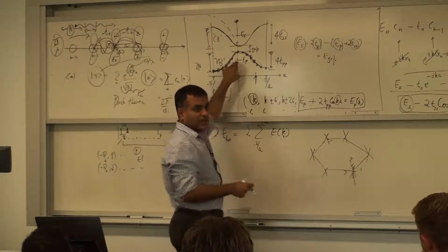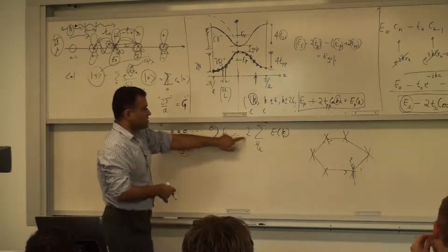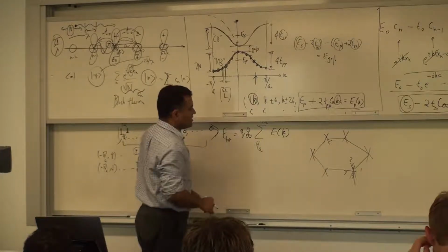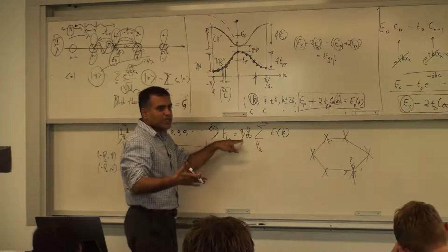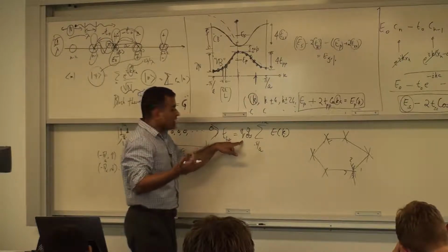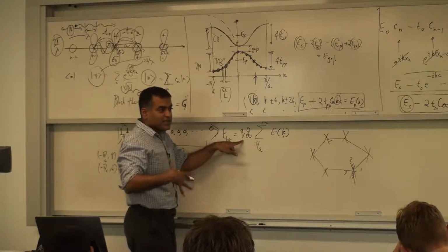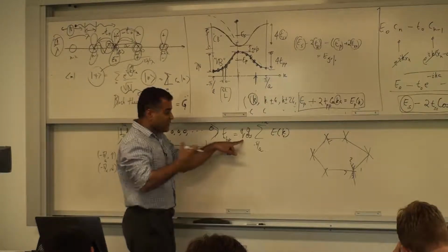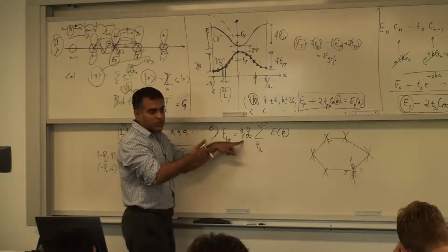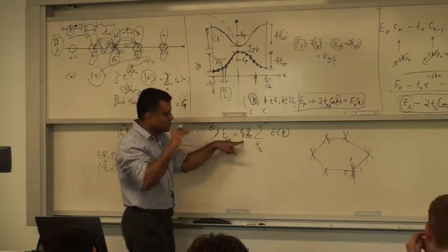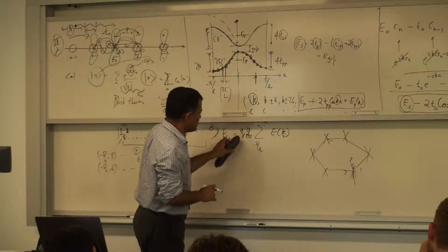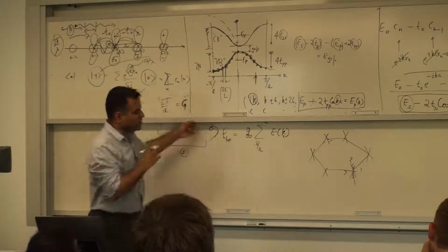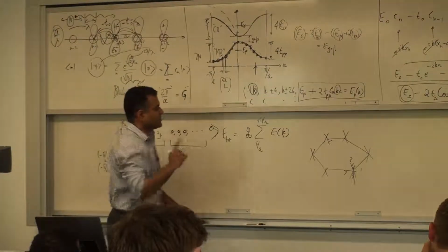And that's called the valley degeneracy. So you can add it here. This is your spin degeneracy, and that's a valley degeneracy. Once the band structure is done, you know what your valley degeneracy is. In silicon, for the conduction band, it's 6. There are 6 of them. In gallium arsenide, gallium nitride, it's just 1. In graphene, it's 2, and so on. Monolayer molybdenum disulfide is 2. So valley degeneracy also comes in here. Here I'm keeping it simple, saying it's 1 just for discussion's sake. But yes, that's another important thing.